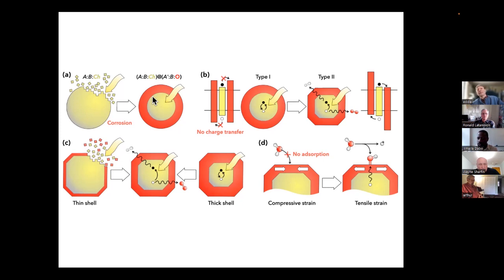And the reason why we think we can do that is because the material within the same chemical family, through the distortion of the lattice, we're able to tune the transparency and the stability. So within the same chemical family, you can interface two materials nicely because they will have the same structure, and then ensure that you protect the material against solar photocorrosion. And that's very much the next step along the development of those materials. I told you about how we can generate many materials, but now how do you practically design structures that would be resistant to corrosion and at the same time photoactive?